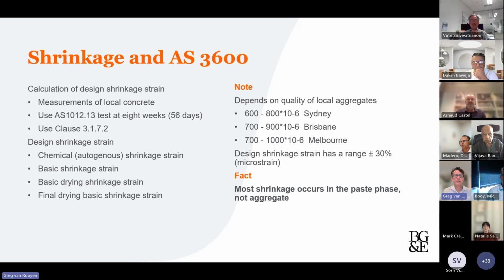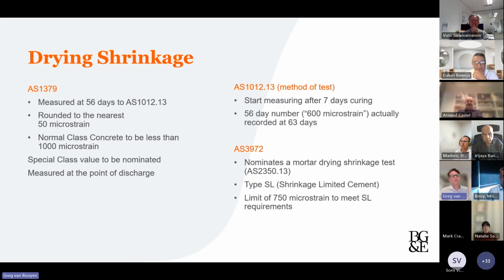I guess the key thing though is the aggregate doesn't shrink much. And it's the paste in the concrete that shrinks. So the drying shrinkage is a 56-day test rounded to the nearest 50 microstrain, and for all normal class concrete needs to fall below 1000 microstrain. Now, the origins of the test are really around selection of aggregate and ensuring you have a stable aggregate in the concrete, less so about the actual concrete performance.